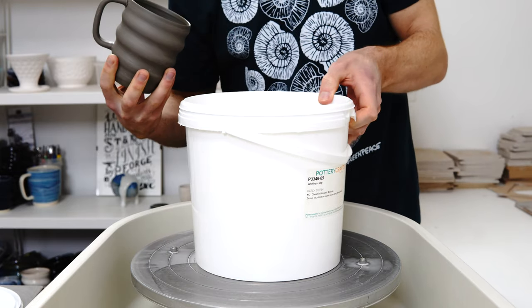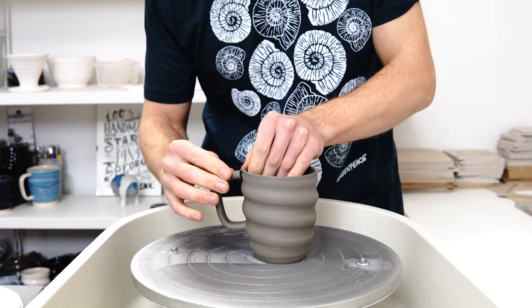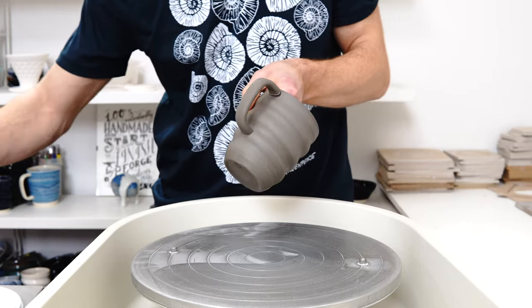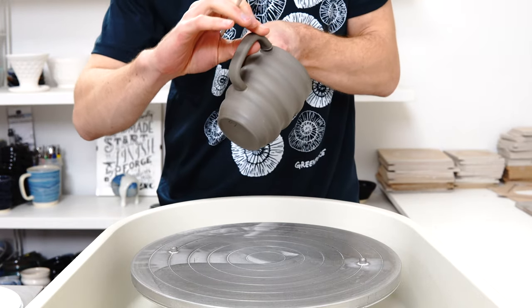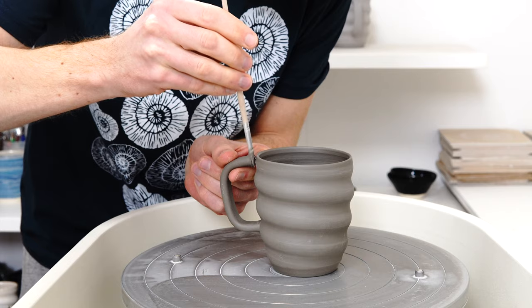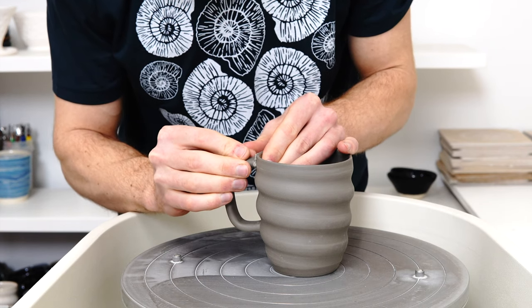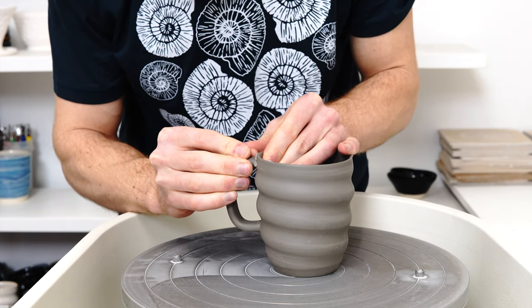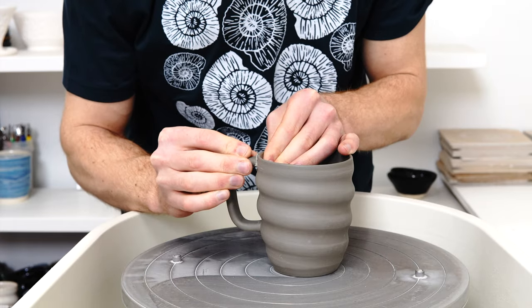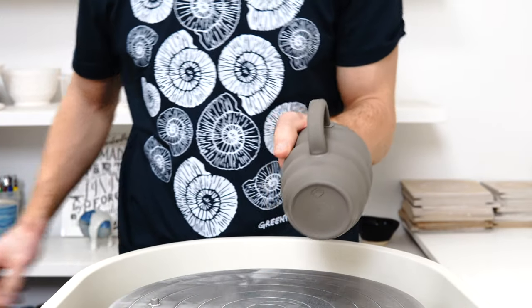It's about a week later and the mug has rehydrated to the point of being soft plastic clay again. I'm not saying this is the way to go about making mugs, but if you get some slip that isn't mixed up too thick and reapply it — really pressurize and wiggle the joint to work the clay into each other — yeah, that's better, that's not moving.